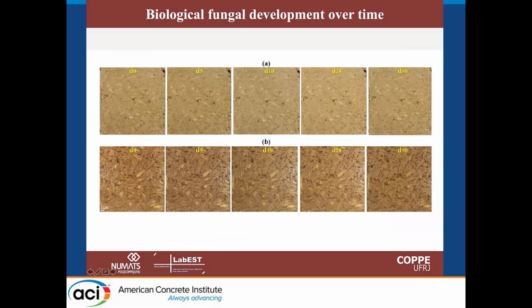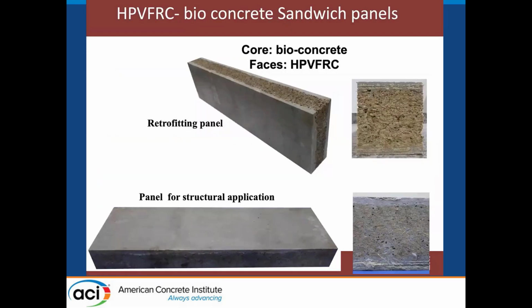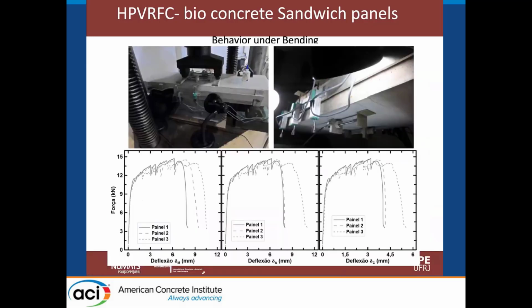Sandwich systems are already being tested using aligned fibers in the extremity composite. In the core, we are using lightweight bio-based concrete. And this material behaves very well. This is a work that I supervised together with Professor Joaquim Barros in a European project. And you see here very beautiful post-cracking behavior using this sandwich panel that now we are starting to plan to develop structural systems.